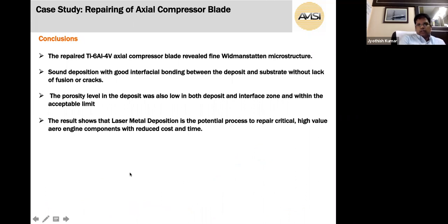So the conclusion part of the axial compressor blade repair, what we observed, says that the repaired Ti6Al4V axial compressor blade revealed a fine Widmanstätten structure, which is on par with the literature as well as the basic metal structure of the Ti6Al4V alloy. And it also showed the sound deposition with good interfacial bonding between the deposit and the substrate without lack of fusion or cracks. That is a very important factor, because I also showed in my previous microstructure, the bonding between the material and the deposition was very good, with no pores, cracks, whatever it is. And it was completely dense deposition.